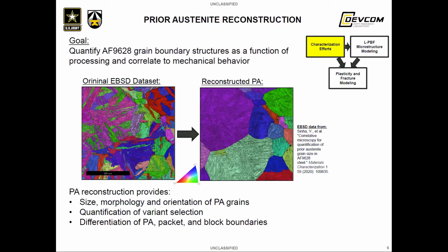An example of this is given right here on this slide. On the left, you have a subsection of the data set that was shown on the previous slide. On the right, you have the martensite laths that have been grouped into their parent austenite grains. The orientation of the parent austenite grain has also been back calculated, which alone provides a wealth of information about the microstructure. You can observe the morphology, size, and texture of the austenite grains. Knowing the parent austenite grain that each martensite grain came from allows you to identify those packet and block boundaries that I mentioned previously. Finally, you can quantify variant selection behaviors.